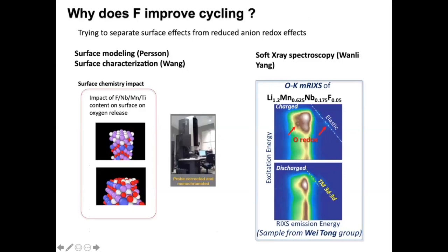This is in Kristin Persson's group and surface characterization by Wang Liang at LBNL, which are showing that there's clearly a small amount of fluorine segregation to the surface. And again, fluorine as an anion really cannot be oxidized unless you go to 6 volt. So you may have some built-in surface protection here in these materials, because some of them still have bulk oxygen redox, but not surface oxygen redox.